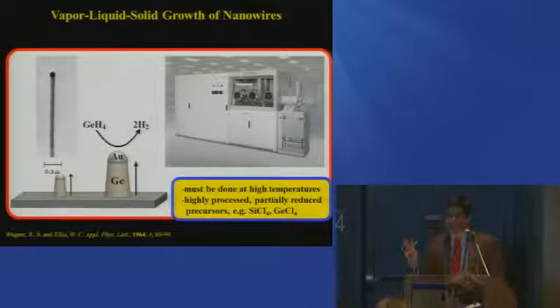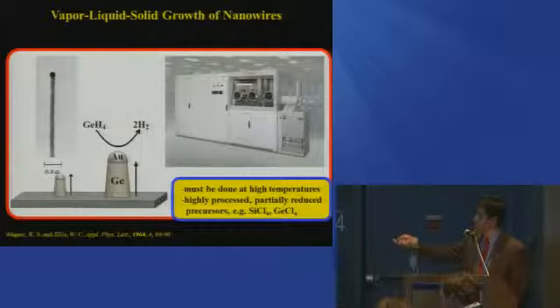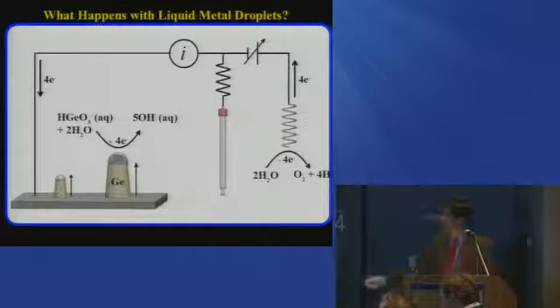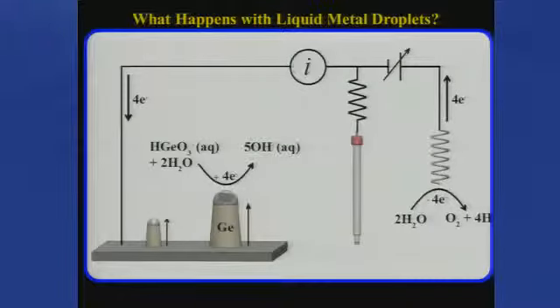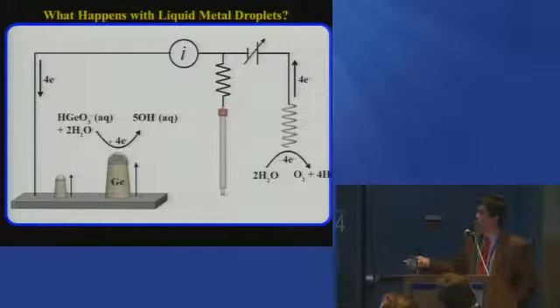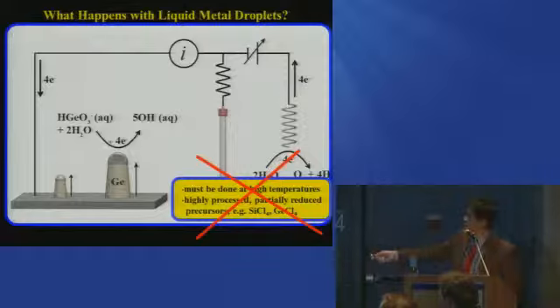And our idea was, aha, this might be an in for us, because if you think about what they're doing, it's exactly what we're doing, except we could do it like this. We could throw out all that high temperature chemical vapor deposition equipment. We can throw out all that high energy intensive precursor chemistry, and we can do the same idea but do it with a potentiostat, at least in our case, where we have our working electrode that's now dotted with little micro or nano droplets of liquid metals. And the idea is that we can nucleate or grow individual nanowires at will. And by doing that, we can bypass all this other stuff that we'd rather get rid of.